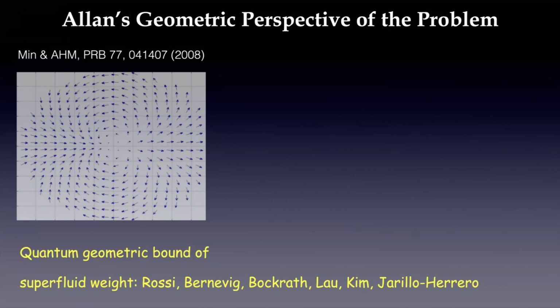So I talked to Allan a couple of years ago, and Allan instructed me that we should calculate the finite momentum susceptibility of the system, and indeed my student Tianyi, where's Tianyi? Okay, he's here. He did the calculation. The result is indeed very beautiful. The zero momentum term of the susceptibility is actually negative. That means the ordered state is paramagnetic with respect to the electric field. The electric field can kill that state. However, the finite momentum term is positive, with a lower bound. The lower bound is given by the valley Chern number, which is basically half of the winding number of the non-interacting system.